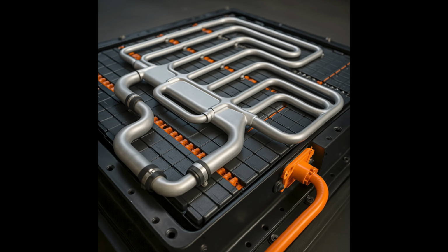Why does this matter? A coolant system's failure doesn't cause immediate thermal runaway, but it sets the stage. As internal pack temperature climbs, passive safety margins erode quickly. There have been cases where a blocked coolant channel can cause cell-to-cell variation of over 20 degrees C, enough to trigger premature aging and even lead to thermal events under load.